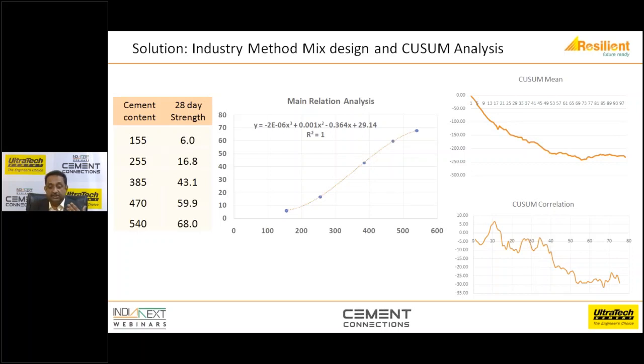Now, this is also using a correlation where you predict from a 7-day to 28-day what is the strength required, and before you actually expose yourself to 28 days of production, you will be able to take quicker decision. This is actually not only monitoring the quality. My experience with using CUSUM in India is that you save around 30 to 40 kilos of cement per cubic meter because you are able to exactly monitor the performance and put things back into place.